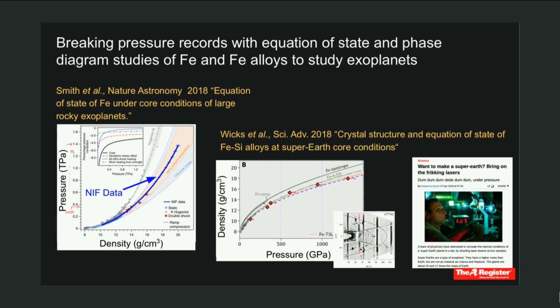Some examples of recent work that I've done is looking at the equation of state of iron at super high pressures. If we compare the compression of ramped iron and ramped iron-silicon alloys to extrapolations from lower pressures from diamond cell, it's actually quite surprising that the room temperature descriptions that were measured hold up quite well when you extrapolate to higher pressures. And that mostly speaks to the fact that although we're following what's closer to an isentrope rather than room temperature, the knob of pressure is so great that it dominates the volume. And so thermal expansivity is much smaller, much less important at those high pressures.